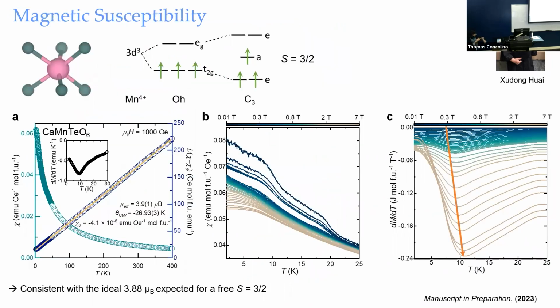Okay, so let's look at the magnetic susceptibility here. It's Mn 4+, you can see from the chemical formula, and the spin is 3/2. So the magnetic susceptibility, and here the revised analysis resulted in the effective moment 3.9 μB, which is consistent with the spin 3/2 system.